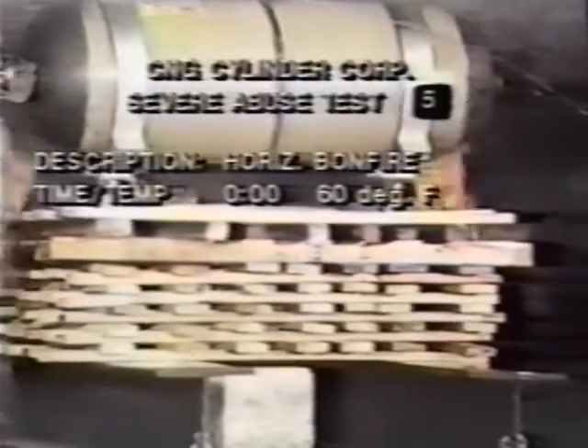The fuel tanks, made by the CNG Cylinder Corporation, bring an exclusive double-redundant safety design to this high-temperature situation. The aluminum itself has a melting point of 1,200 degrees Fahrenheit, while the composite reinforcement that doubles the strength of the cylinder against internal bursting maintains a usable tensile strength to about the same temperature. While the heat is concentrated at the bottom of the cylinder, the high thermal conductivity of aluminum distributes the heat quickly. And although aluminum anneals at high temperatures, cylinders subjected to these bonfire tests withstood hydrostatic burst tests above a minimum burst pressure of 7,500 psi.